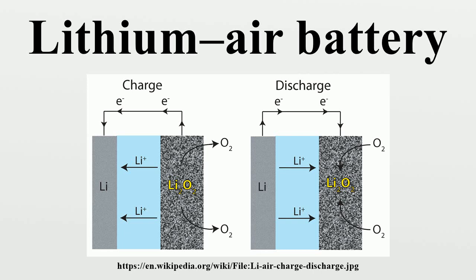The development of new cathode materials must account for the accommodation of substantial amounts of Li2O2 or LiOH without causing the cathode pores to block, and employ suitable catalysts to make the electrochemical reactions energetically practical. Dual pore system materials offer the most promising energy capacity. The first pore system serves as an oxidation product store. The second pore system serves as oxygen transport.